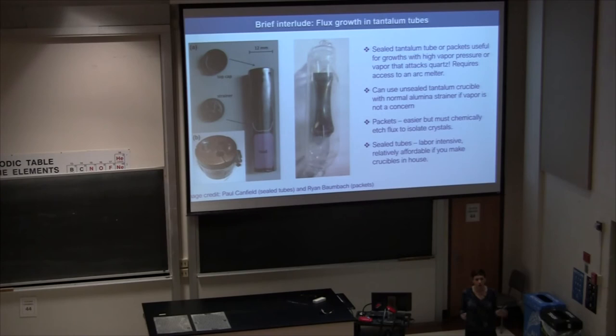So you have two options for how to approach tantalum growths. You can use the packet method, shown here, where you take a sheet of tantalum and fold it up, and then use an arc melter to seal one of the ends. You seal one end in advance, add your material, and then seal the other end. Since the arc melter is under, say, an argon environment, there's no air trapped inside your growth. Then you seal your tantalum inside of a quartz tube. You have to do that because the tantalum by itself, if you just threw it in the furnace, is going to oxidize and expose everything inside your growth. So unfortunately, even though you have the enclosed environment of the tantalum, you still have to add the extra step of quartz sealing. The disadvantage of the packet method is that it has no strainer,